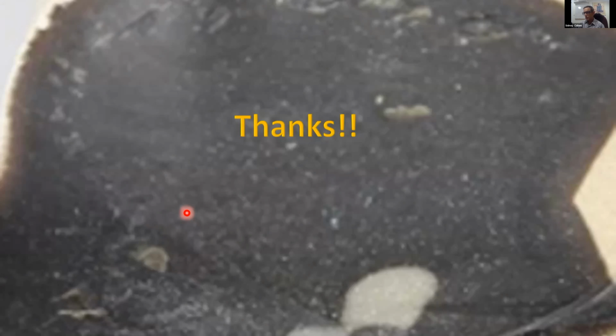So the point of these kind of mechanical measurements that we do is they're very, very localized. If you look at a typical contact radius that we're talking about, it's just a few nanometers. The depth of it is about 3 times that contact radius. So we're probing down into the surface really very minimally, maybe 10, 20 nanometers. And we know that the volume of those is much greater.